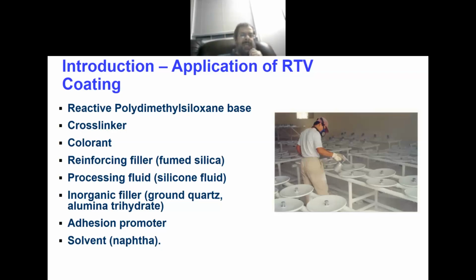Now, what is an RTV coating? Basically, it is a polymer material, polydimethylsiloxane base. There is a cross linker, there is a colorant, there are fillers. We use fillers here to enforce certain mechanical and electrical properties. We use fumed silica for mechanical integrity. We use alumina trihydrate, ATH, for better thermal properties for the material. We use adhesion promoters so that we have very good adhesion between the coating and the surface of the glass or the ceramic insulators. So this is a sort of introduction about why we reached this RTV coating business.